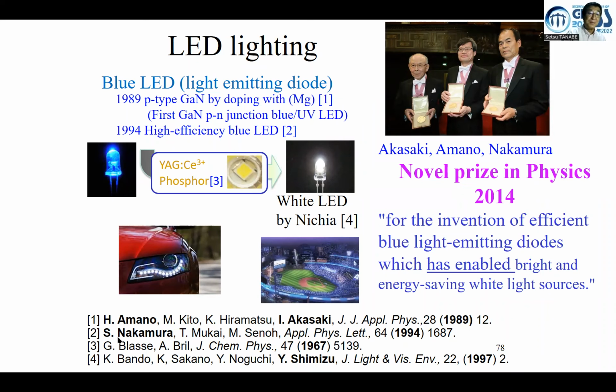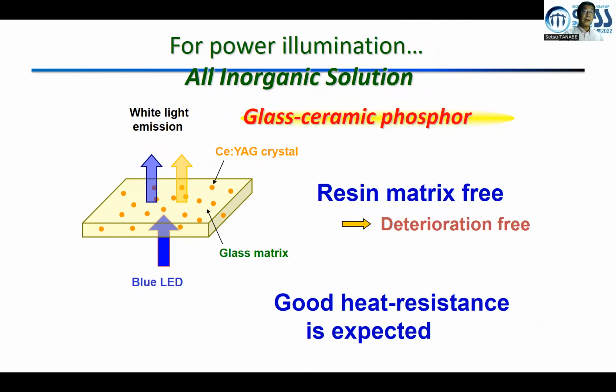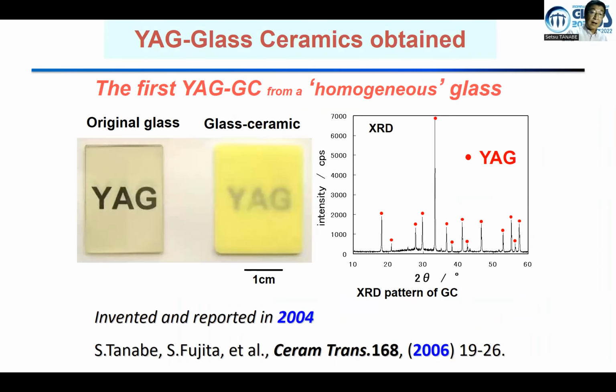And YAG cerium was invented in Blasse, and Dr. Shimizu utilized this phosphor to combine with the blue LED, the very strong LED invented by Nakamura at the Nichia company. So we took a slightly different approach to solid state lighting. We developed glass ceramics with precipitated YAG cerium nanocrystals. In this case, the matrix is silicate glass, which has much better durability and thermal resistance than silicone or powder. This is a picture of the as-made glass containing cerium after ceramization, which has the same color as YAG cerium phosphor, but much stronger.